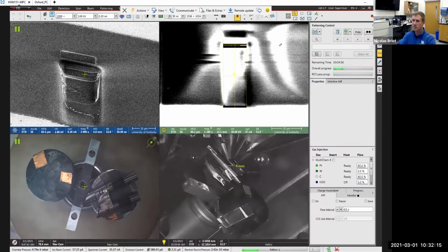Hopefully that's deep enough. When you start getting into the 20 microns-ish depth, that's kind of the bad spot, because it's a little shallow to get a good signal when you mechanically polish things. I mean, you can, depending on the material and all of that, but it's starting to be a little deep for the FIB. So usually the cuts we make with the FIB are more like in the first 10 microns.